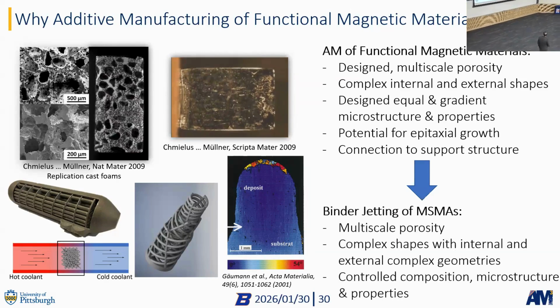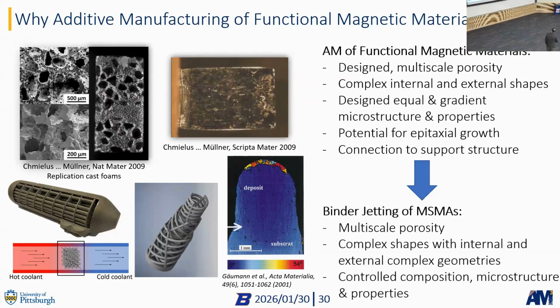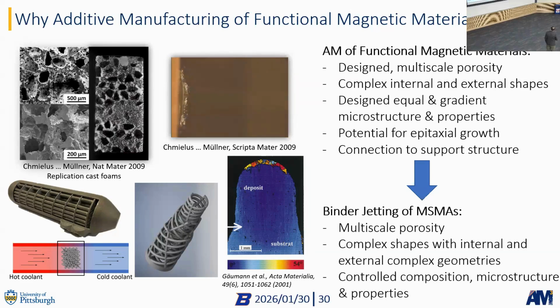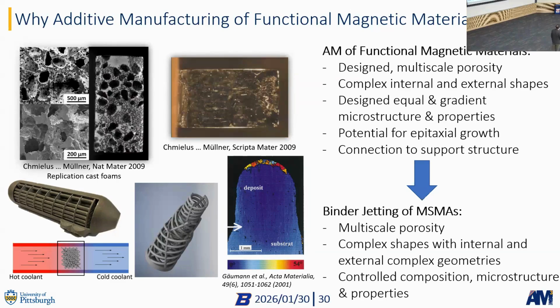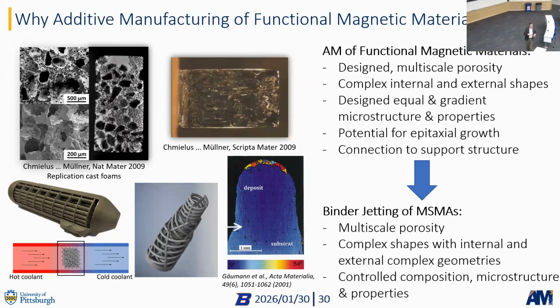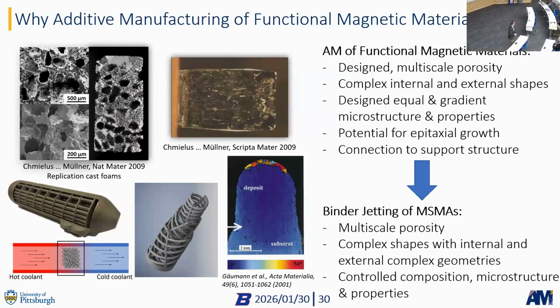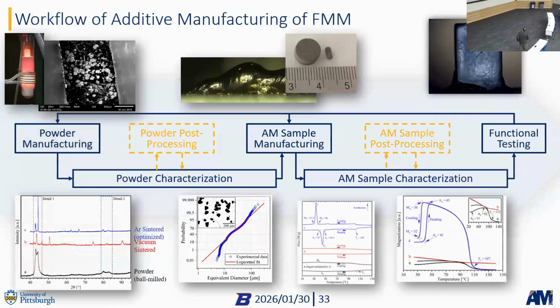Binder jetting, though, on the other hand, is really useful for this porosity, complex shape, and what is really important for us is the controlled composition, microstructure, and properties. And that's what I will talk about today, binder jetting of these materials. So in my lab, we are making powder, we are characterizing it, potentially post-processing it. We print AM samples, then characterize them, potentially post-process them, and do functional testing, right?